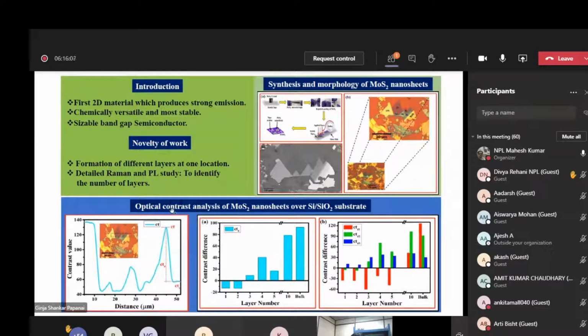calculated the optical contrast by using the image software, and here you see the CT is the contrast of the MoS2 nanosheets and CTS is the contrast of the substrate, and this profile has been captured in the rectangular region. Further, you see the contrast difference versus the layer number.